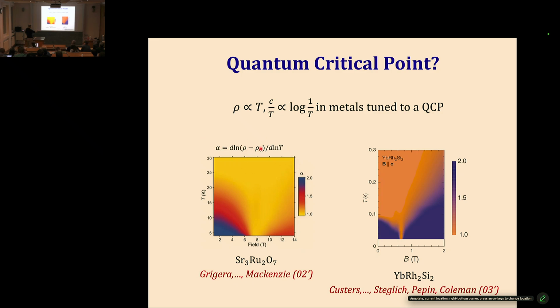Once again, this alpha is the log derivative of the resistivity as a function of temperature, and it crosses over from being Fermi liquid like, T squared, on both sides of the critical point, but then it tends towards 1 exactly at the critical field, and there's this fan-shaped form, which basically sharpens to a point towards 0 temperature. So this is qualitatively what you expect if there's a quantum critical point. At T equals 0, the system is either Fermi liquid on both sides or something else exactly at one point, at the quantum critical point. And as you raise temperature, the distinction blurs and you get this fan-shaped behavior. So it's a very natural way to think about the breakdown of a Fermi liquid.